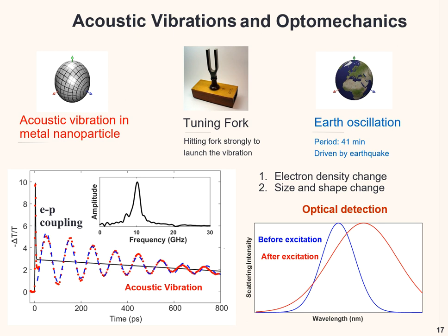For example, I plotted this single particle transient absorption kinetics. What we see here is a fast decay. This is the electron-phonon coupling time. I've spent a lot of time on it today. We also observe these collective oscillations of the nanostructures. This oscillation is because of these acoustic vibrations. The frequency in a single nanoparticle is about 10 gigahertz.